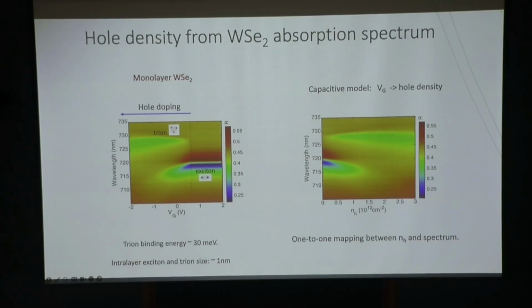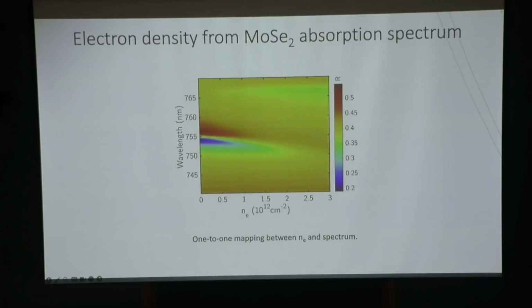After this calibration, we can perform optical spectroscopy and directly read out the hole doping in the system. So we have a remote way to know how many holes we have in the layer. The same can be done for electrons. Here I show the spectrum, again reflectivity as a function of wavelength, and the electron density. You can see the exciton signal change and a new trion appear once you have finite electron densities. So again, with optical spectroscopy, I can read out how many electrons I have. This is for isolated layers.